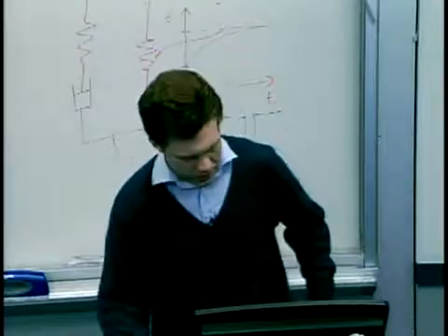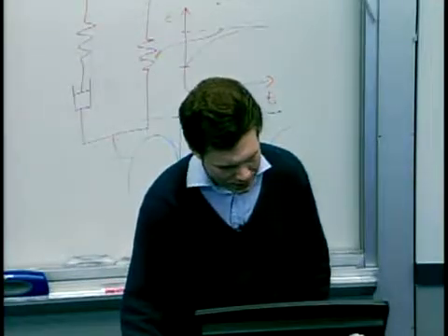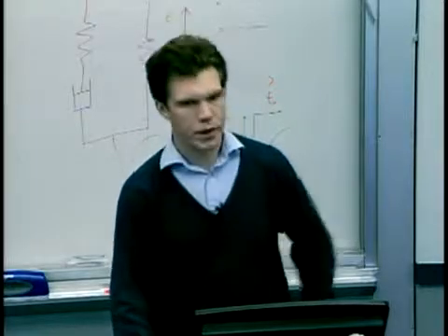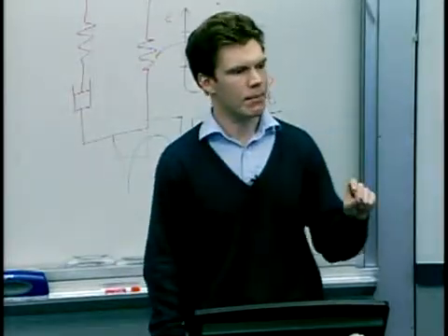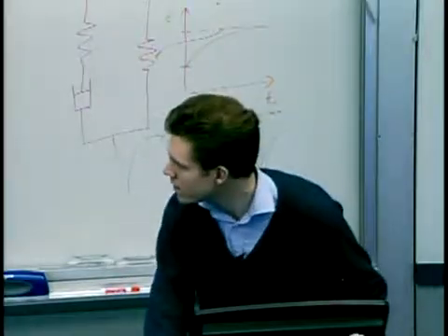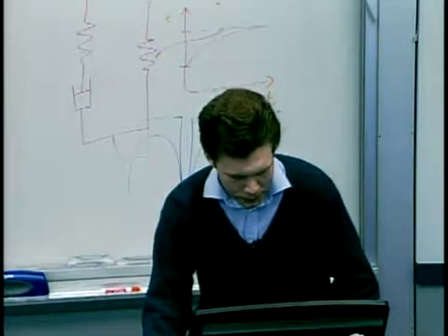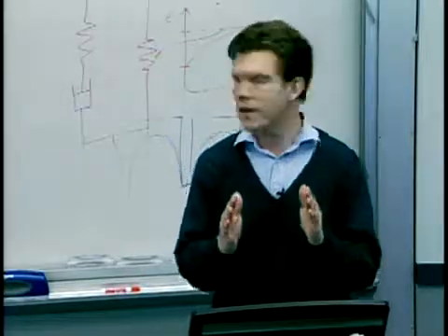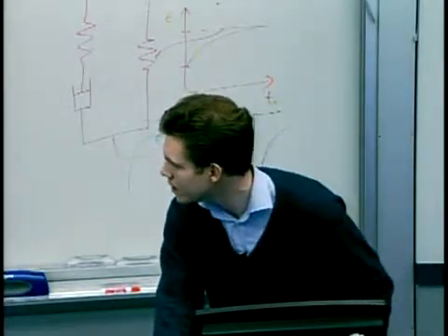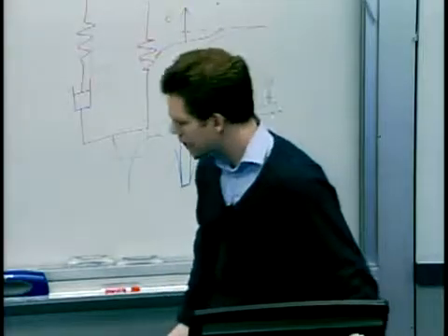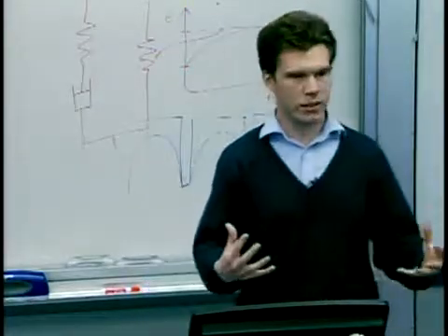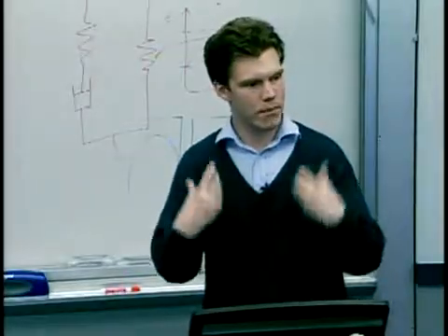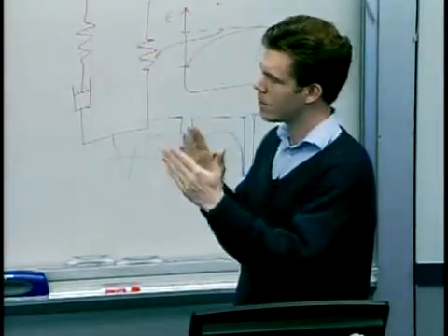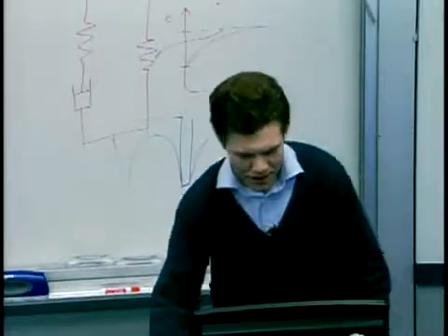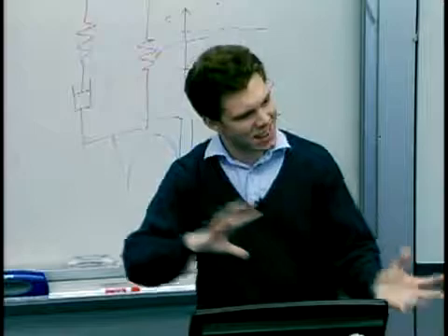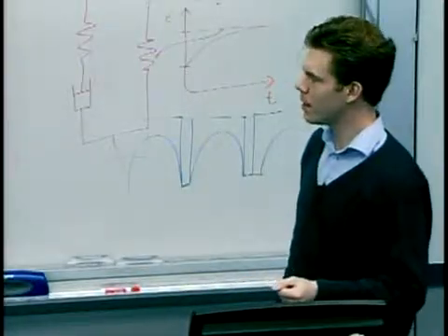And you'll also notice that I put these little black dots on the graph as well, and those are the measured heights of the stamp cavities. So you can see that actually the heights of the stamp cavities fall off for the narrower cavities, and that's associated with the etching process that's used. The actual plasma etch that makes the trenches in the silicon stamp has a harder time etching the narrower trenches. But it's a good sanity check that we're actually measuring the penetration of polymer into the cavities.